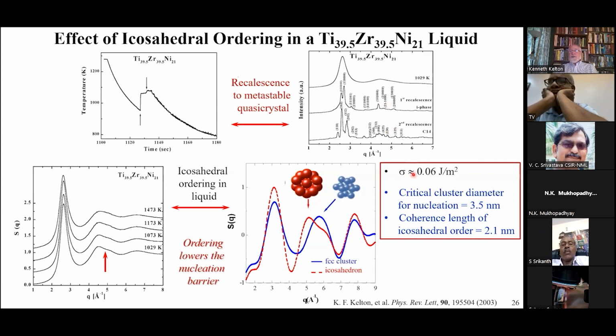And in fact, if you measure the interfacial free energy between the I phase and the liquid from nucleation measurements, it turns out to be 0.06. That's very small. That's much, much smaller than people normally see in liquid to crystal transformations. But even more compelling to me was if you looked at the critical cluster diameter that you could calculate, knowing the driving free energy and the interfacial free energy, it turned out to be about 3.5 nanometers. If you estimated the coherence length from the liquid structure, that turned out to be 2.1 nanometers. These are all rough estimates. So basically, they're the same.